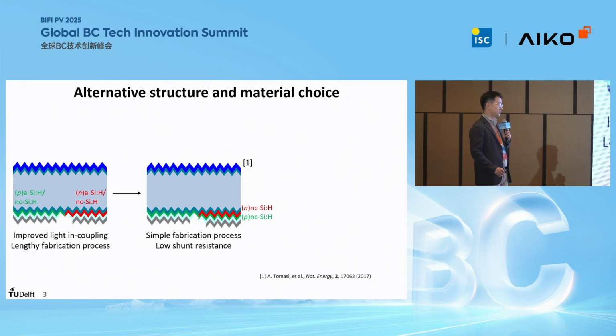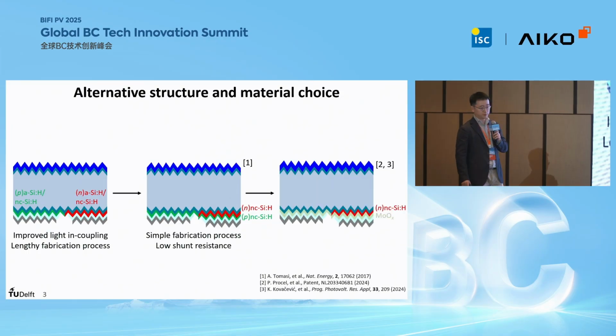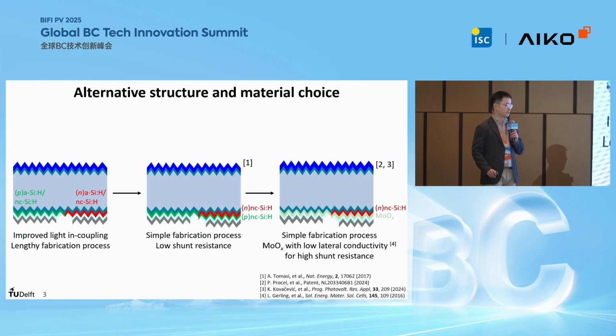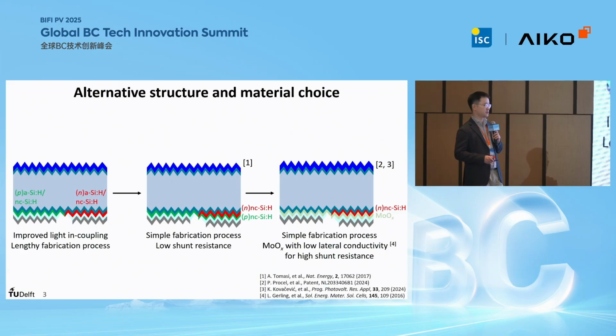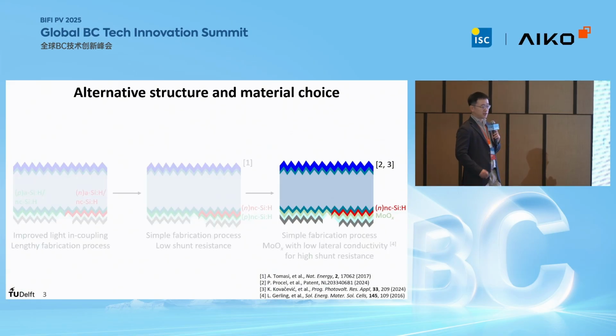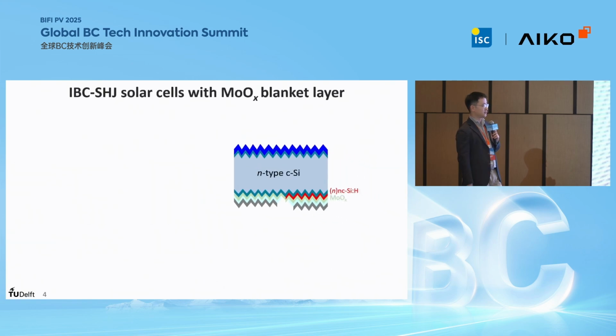of such devices. In our group, we propose, instead of using a P-type nanocrystalline silicon layer, to replace it with a full blanket layer of molybdenum oxide with a thickness of 1.7 nanometer. In this case, it also features a simpler fabrication process, and thanks to the low lateral conductivity of molybdenum oxide, it also enables the device to feature higher shunt resistance. So now let's take a closer look at this device.